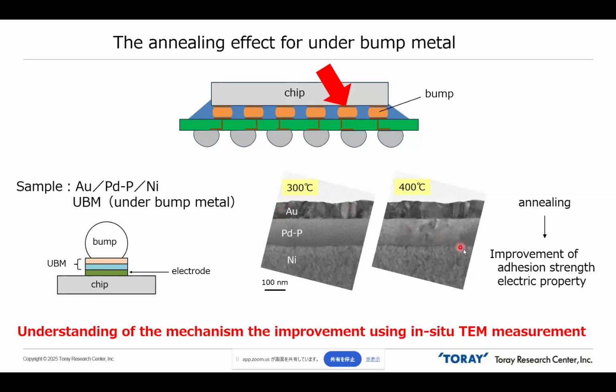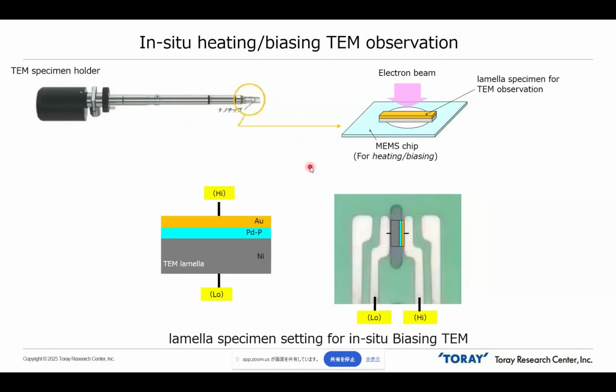Generally speaking, the adhesion strength and electric property can be improved by annealing. So here we try to understand the mechanism of this improvement using our in-situ TEM measurement techniques. In this technique, at first we fabricate a thin lamellar specimen for TEM observation. Then we put this lamellar specimen on this kind of MEMS chip on the top of the TEM specimen holder. Then we can apply heat to the lamellar specimen, and we can also apply voltage to it, as illustrated in this figure.